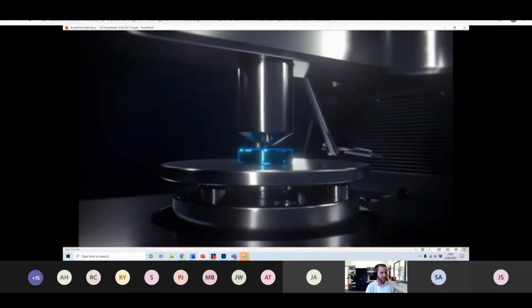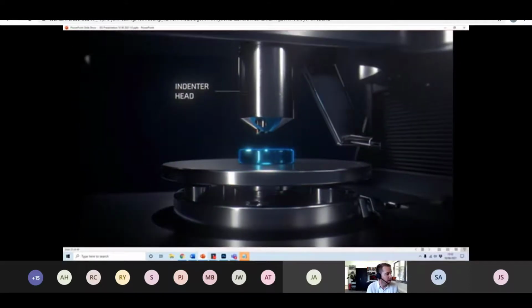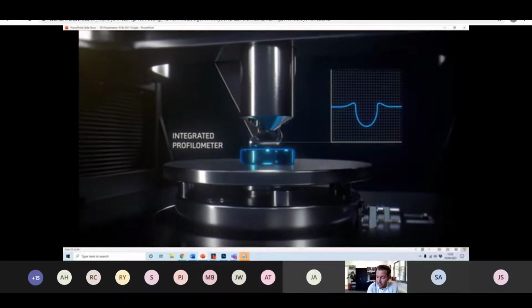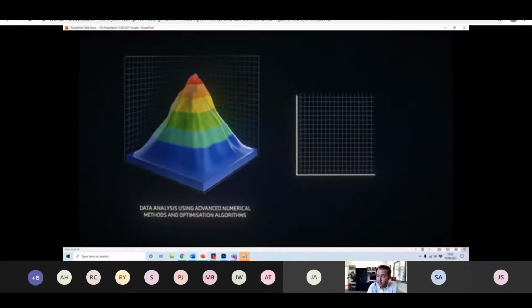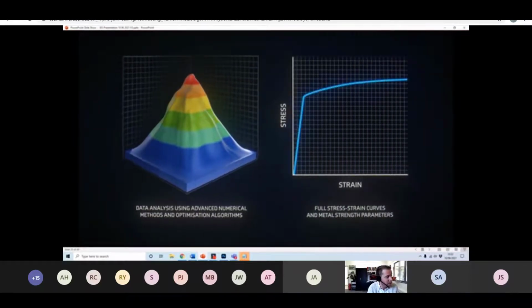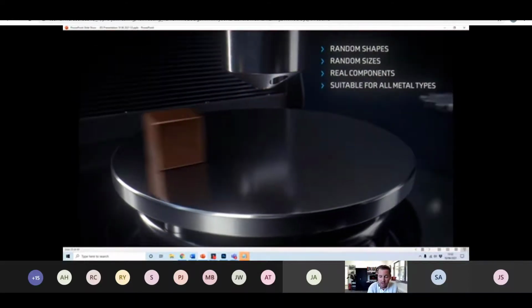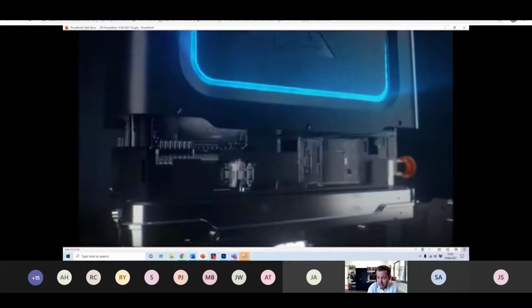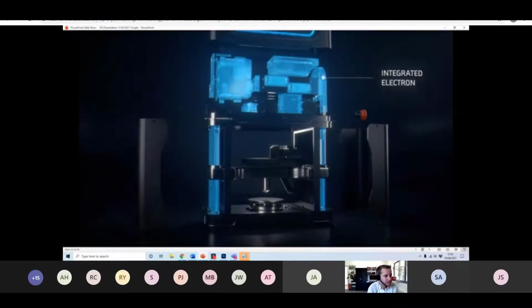Here you'll get to see one of these indentation plastometers. You can see that it looks similar in execution to hardness testing, actually, so that machine there is performing an indent. Only this time we're coming along with the integrated profilometer, and we're measuring the full profile shape because that profile shape contains an awful lot of information, and then it goes into our software package, SnapShape, where we do some clever optimization work and some inverse FE, and we're able to pull out meaningful data like full stress strain curves, strength parameters. We can even calculate hardness numbers if people so want them. And this entire process takes just a matter of minutes.